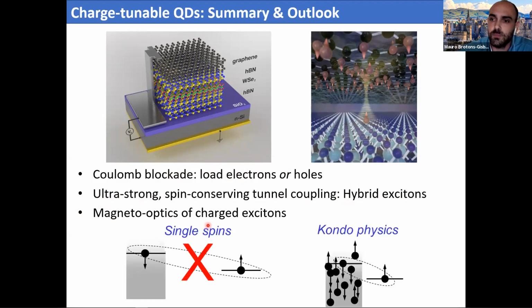But now these results open the doors to new research in two very different regimes. One regime is one in which we try to cancel the coupling between our localized state and the environment, to have isolated spins to be able to manipulate them. This can be done simply by changing the number of layers of this tunnel barrier, so we need to choose a thicker hBN layer. But we can also go to the opposite limit and investigate new Kondo physics. If you think about what the van der Waals platform offers, we can replace this top contact by another material, for example a ferromagnet with spin polarized carriers. So I think there are nice things to do with this material platform.